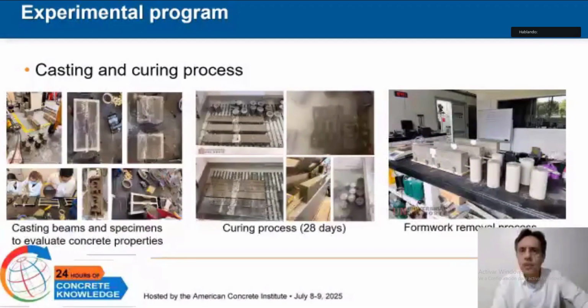The second sequence shows the curing process. All specimens were stored under controlled humidity and temperature conditions for 28 days under ASTM C192 guidelines. This step was critical to ensuring the development of full mechanical properties, especially for the UHPC mix.